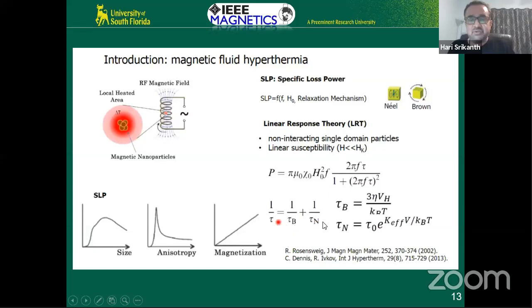In fact, there are two relaxation times that go in there. One is the Brownian, the other one is the Néel relaxation time. For example, the whole particle itself can have mechanical motion, and that's your Brownian time scale. And of course, the magnetization vector alone can coherently rotate when you apply an external alternating field, and that is your Néel magnetization. So a combination is important, but it's the Néel term that is more important, because obviously particles can be arrested, right?